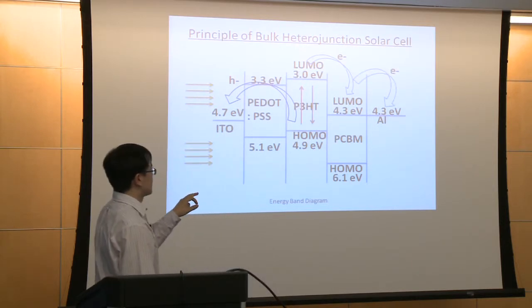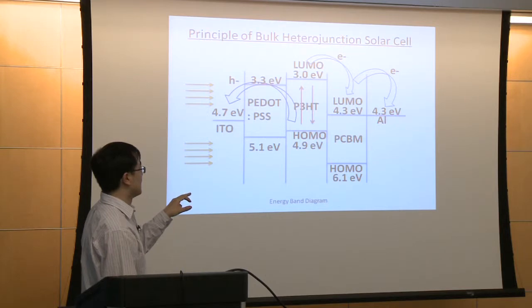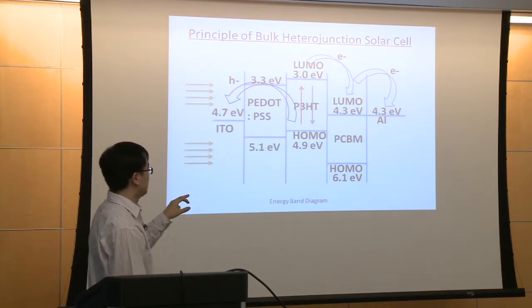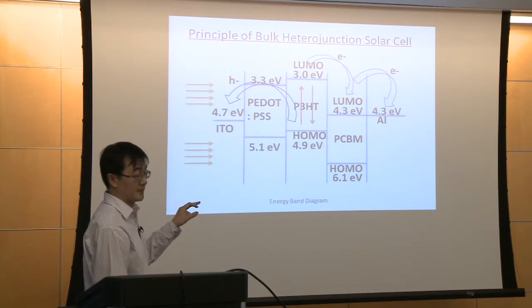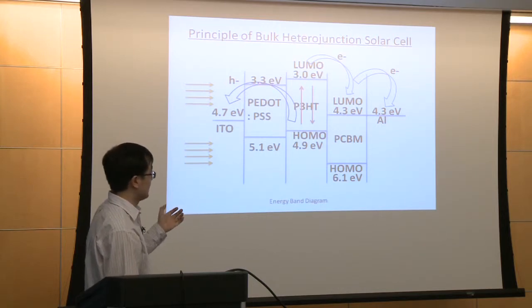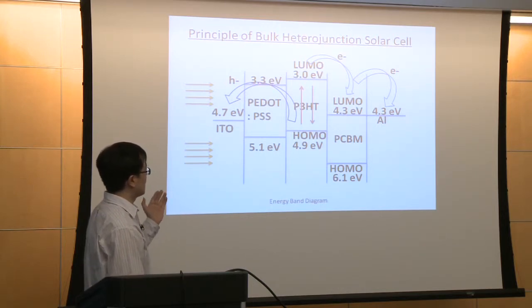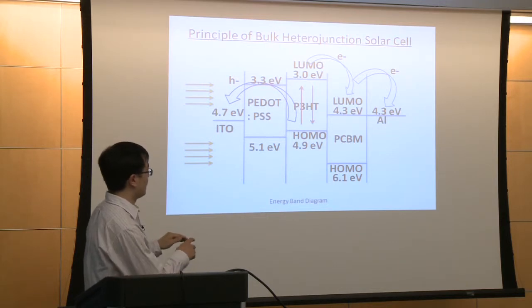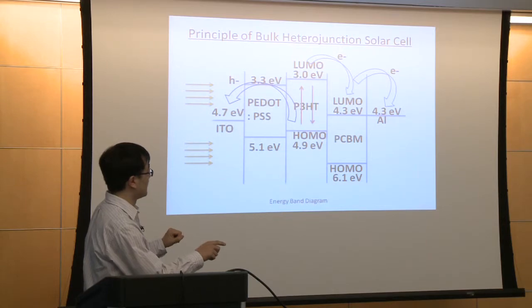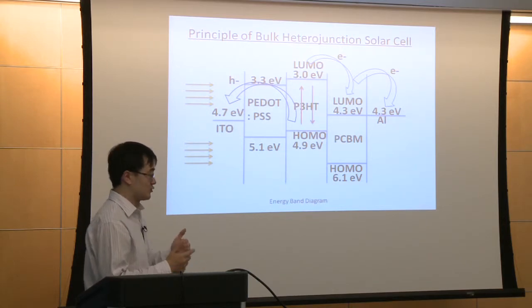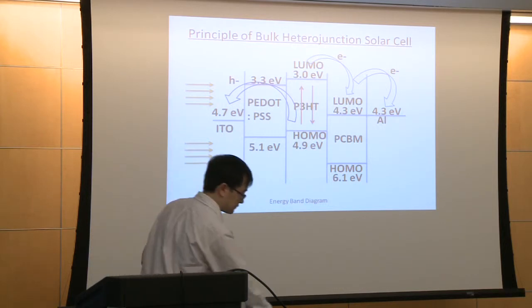And also you may notice that the work function of aluminum is about 4.3 eV. It's the same as the conduction band of the PCBM, which is the electron acceptor, which means there's no band gap for the electrons to jump from the PCBM to the aluminum. So the electrons can move freely. And in this way, the electricity is generated.